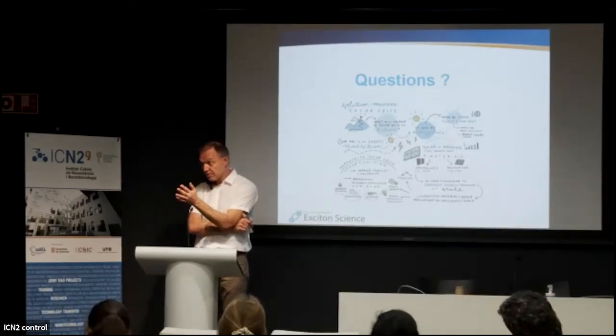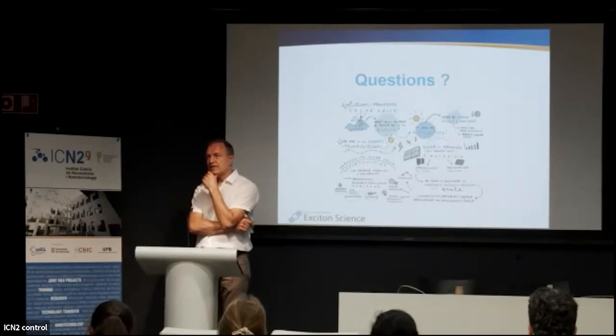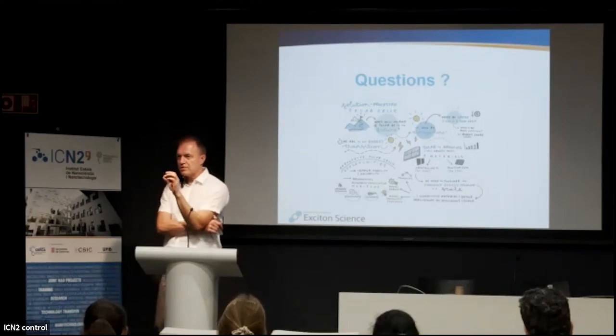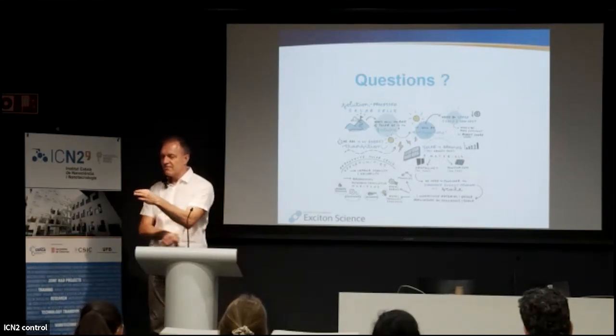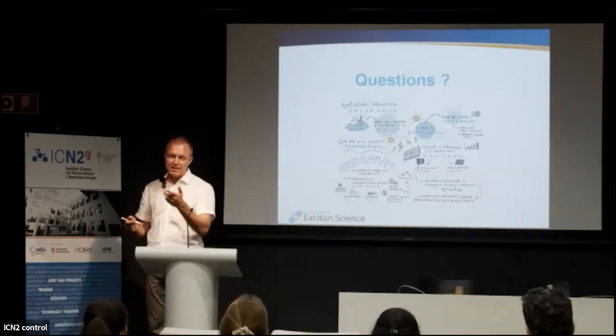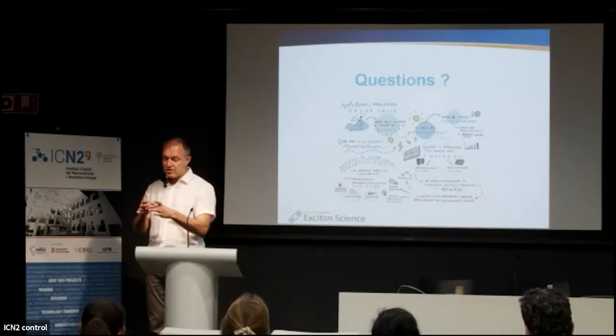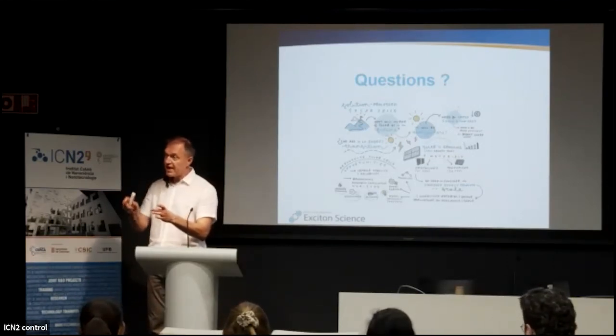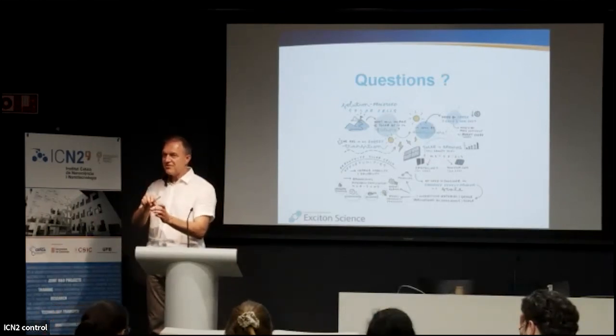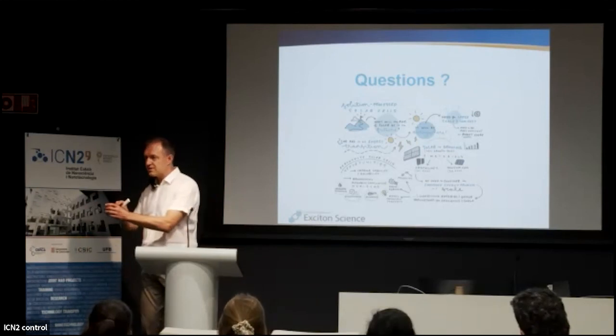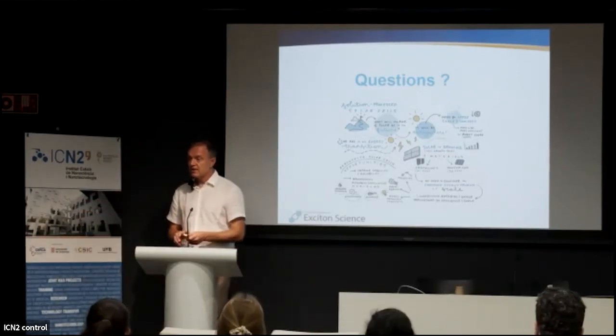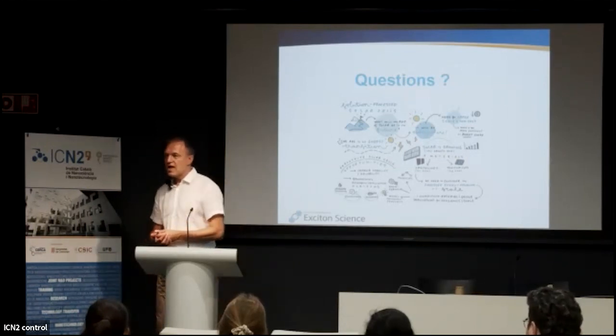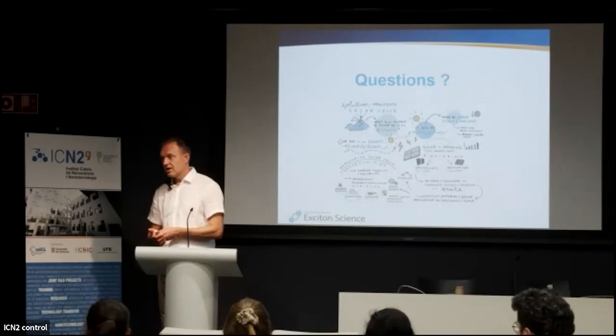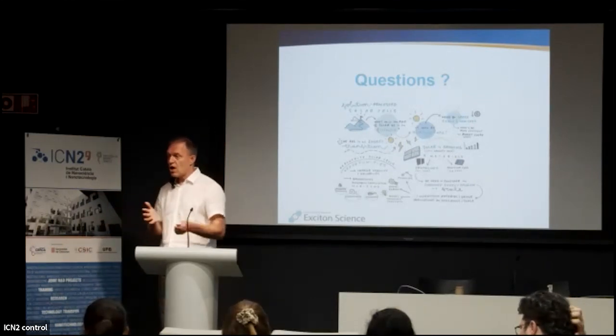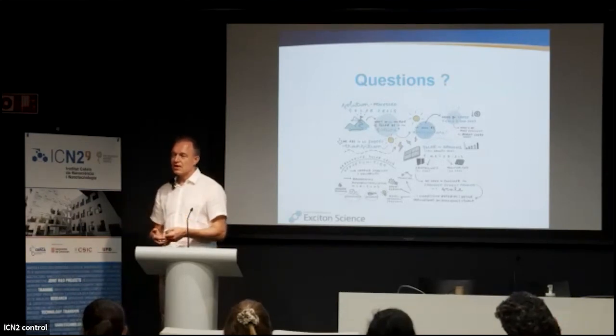You have additives, as you say, that can stop that mobility. The other way is, my understanding is that it is not necessarily the halides that are mobile, but strictly speaking the lack of one, the vacancy. Once you have a vacancy, something can hop in, and that hopping of a halide from where it is into the vacancy is de facto the displacement. So you actually have the vacancies moving around. If you can make a material that is entirely free of vacancies, you should not have phenomena such as phase segregation, because your ions can't move anymore. So you're telling me that in your crystals you probably have some vacancies, and that's why you observe that movement.